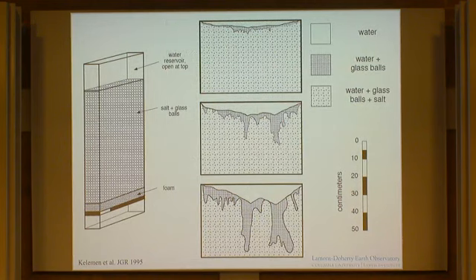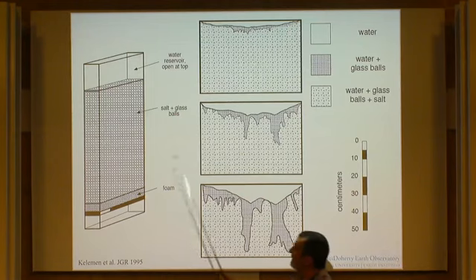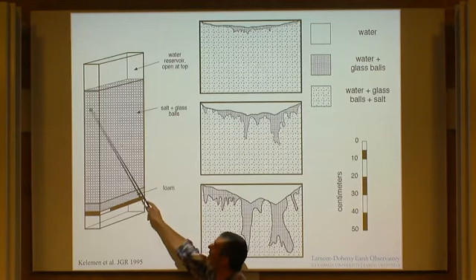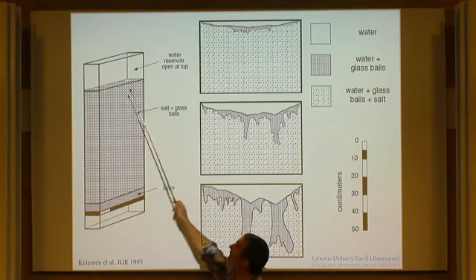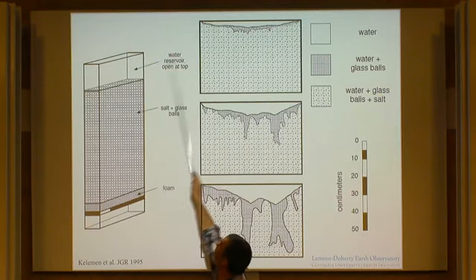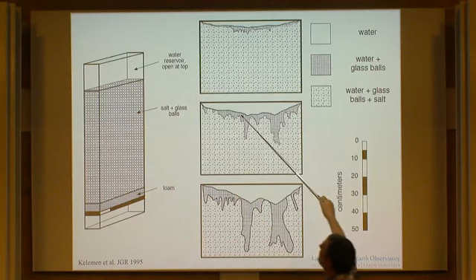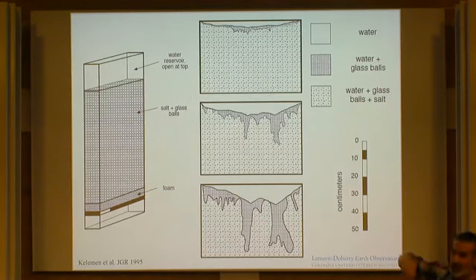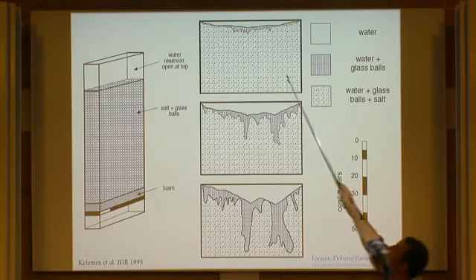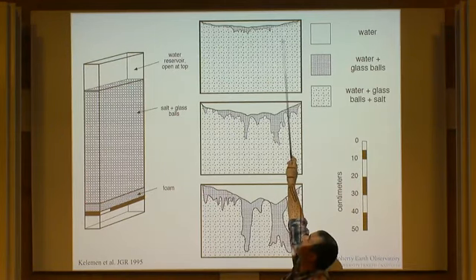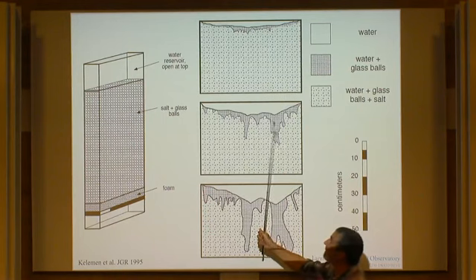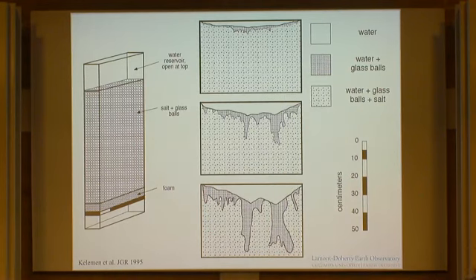Anyway, we fooled around with, it's kind of an ant farm, so we made what you could call a Hele-Shaw cell, it would be more polite, but it had glass balls and salt in here, and we ran tap water through it. And you can watch these dissolution channels grow. The wavelength of the channel spacing starts out very short and gets longer, and the channels get bigger, and there's winners and losers, and so on.